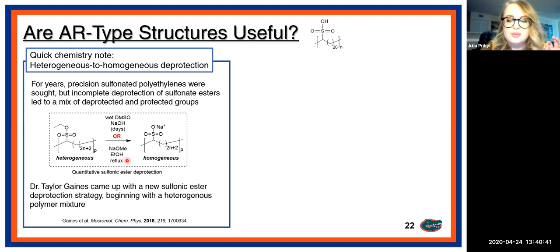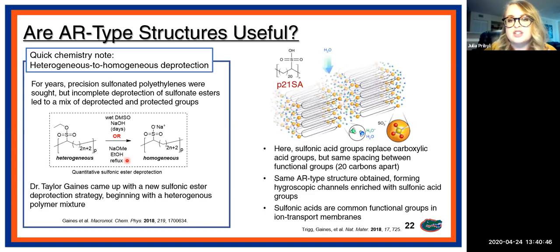So this chemistry is really what enabled the functional polymer that I'm going to talk about next, which is using this precisely sulfonated polyethylene to prepare ion transport membranes. So here we have a sulfonic acid group, which replaces the carboxylic acid group that I talked about previously, but they're the same spacing apart. They're every 21st carbon or 20 carbons apart. And they achieve the same adjacent reentry type secondary structure, which forms these hygroscopic channels enriched with sulfonic groups. And sulfonic acids are common functional groups in ion transport membranes because they are so hygroscopic.